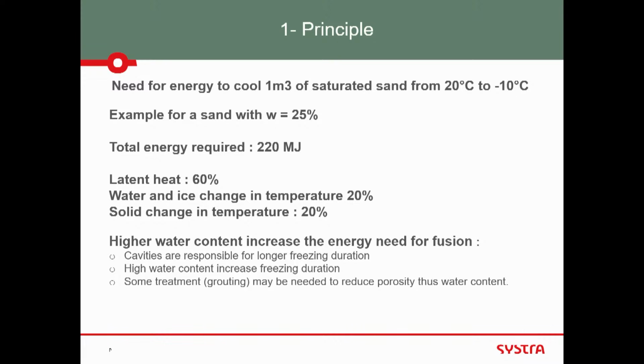The first reason is you decrease the water content, so the quantity of water in the cavity, and in this case, you need a lot less energy for freezing. High water content increases the energy which is required, and in this case, the duration, because the power of the freeze unit is given. So for a given power, if you need more energy, you need more time. And to reduce porosity, some treatment, grouting, may also be needed, always to reduce the quantity of water.